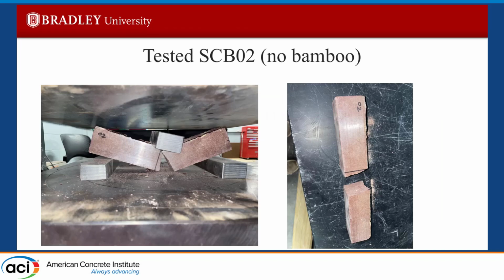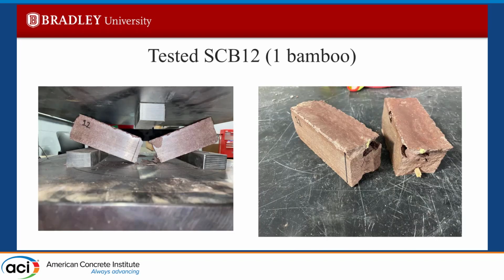So we have some tested pictures already shown. This is a tested specimen with 0 bamboo, and as expected, has a brittle failure. Not much else to show from that one. The next one, we actually go into a 1 bamboo. As you can see, still a brittle failure. As you can see in the right picture, the bamboo just snapped, which is what was expected at the time.